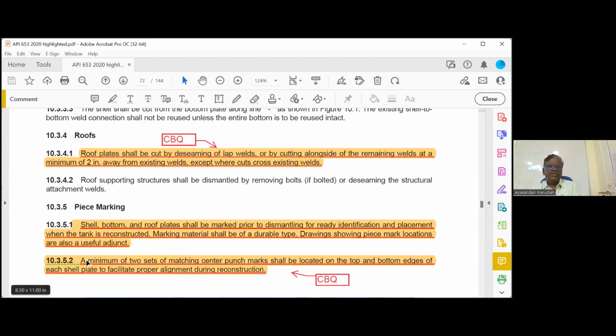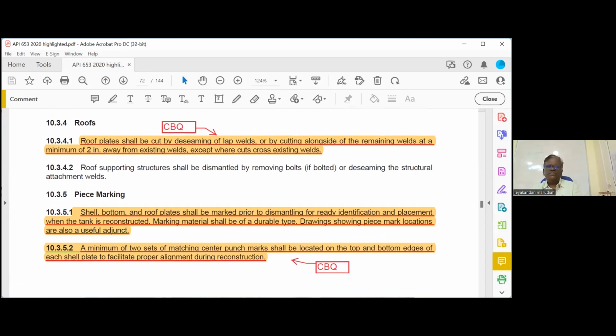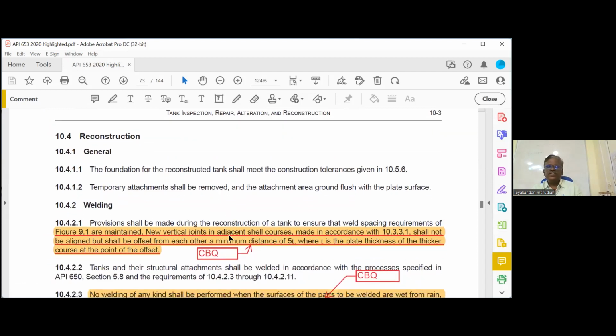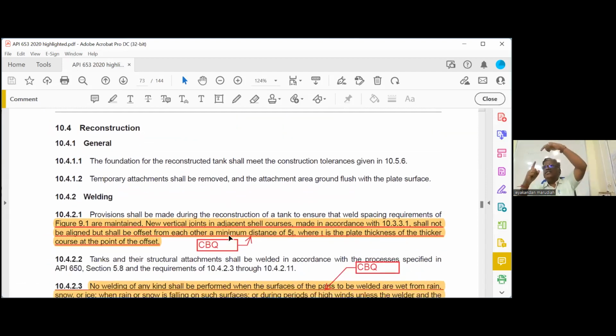Then 10352. A minimum 2 sets of matching center punch marks shall be located on the top and the bottom edges of each shell plate to facilitate proper alignment during the reconstruction. Then please go to the next, reconstruction. Reconstruction, what is the vertical joint stagger? New construction, 5T. What is the T? Thickness of the thicker plate. Same here, same requirement. Highlight this one. New vertical joints in adjacent shell courses shall not be aligned but shall be offset from each other minimum 5T, where T is the plate thickness of the thicker course. That is a closed book question.